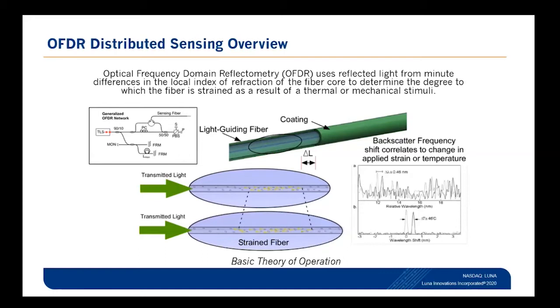And typically we'll look for using it as a strain or a temperature. So if we see a hot spot along the fiber, it's going to cause this backscatter frequency to shift, and then that has a fairly linear correlation to the temperature. And that's how we're able to make the temperature measurement, or the same occurs with strain. When the fiber is stretched to a certain point, that pattern will elongate, and we'll be able to correlate that shift to the amount of strain that's been applied to the test article.